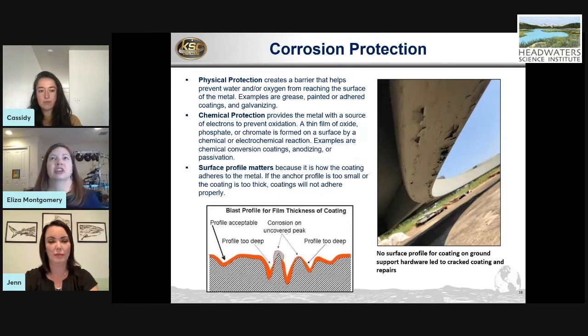Even though it seems strange for something to fall off from the microscopic level, coatings will fall off if they're not adhered properly. And so literally at the same time, you have to understand how the microscopic and atomic level of something works on the surface, and then how it applies to a giant launch structure. So think both ways. But if something is too high and you have a really rough surface, you're not going to get a coating that's even because the coating's going to be too thin. You're going to have pieces of the metal sticking out. This is a great example of ground support equipment that they didn't prepare properly, and the whole thing flaked off. And then they called me and asked what happened. And the first thing I said was, how did you prepare it?